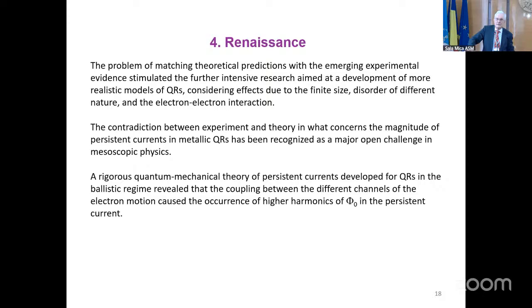The contradiction between experiment and theory in what concerns the magnitude has been recognized as a major open challenge in mesoscopic physics, and therefore it took a big part in the monographs on mesoscopic physics, which were issued in the 90s and in the beginning of this millennium. A rigorous quantum mechanical theory of persistent currents developed for quantum rings in the ballistic regime revealed that the coupling between different channels of the electron motion in a ring caused the occurrence of high harmonics of the magnetic flux quantum in the persistent current, which also were observed experimentally.